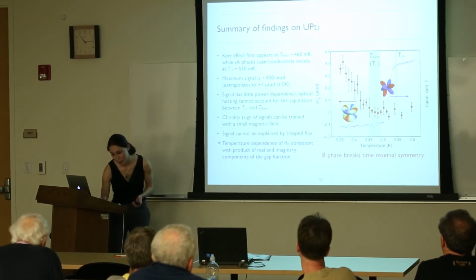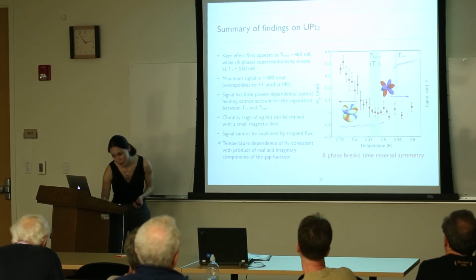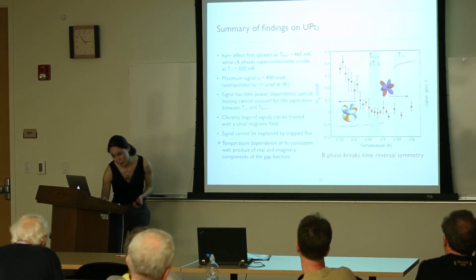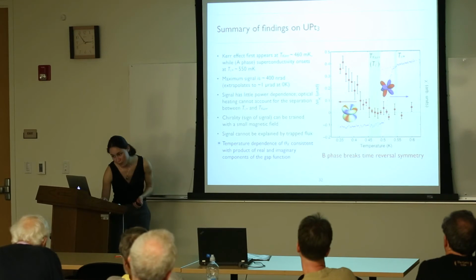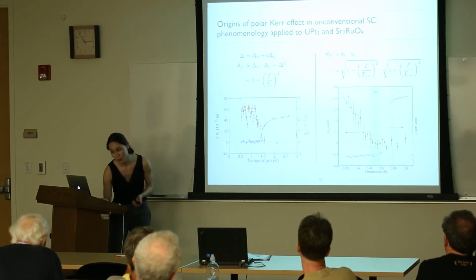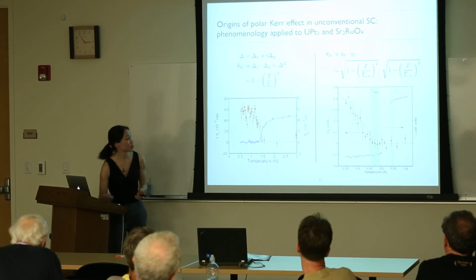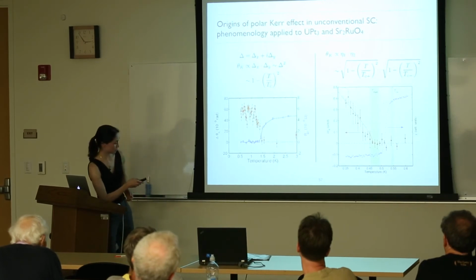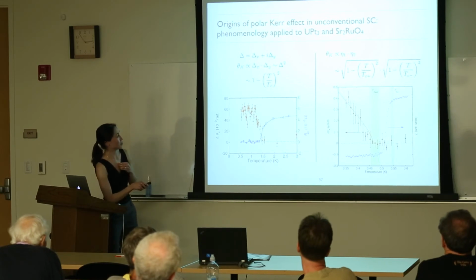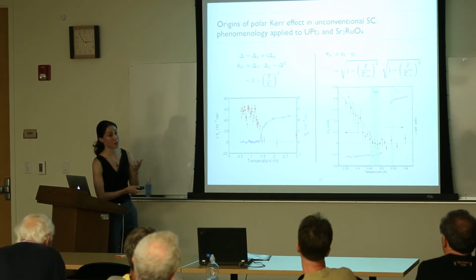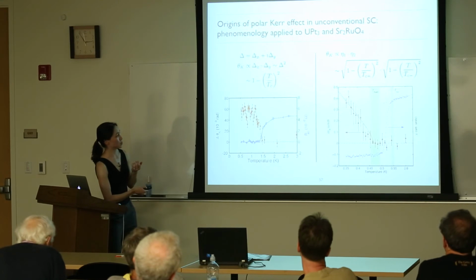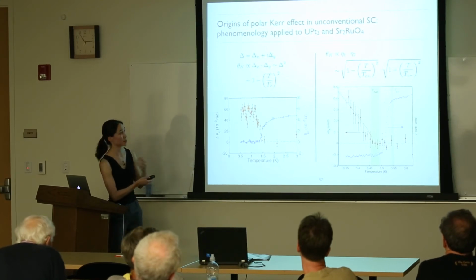So the idea is that this is basically only valid below the second transition temperature, if that makes sense. So this is what we were using, the fact that this doesn't work above Tc minus. But once you go below Tc minus, then you have a piece that presumably came on at Tc plus, another piece that came on at Tc minus.